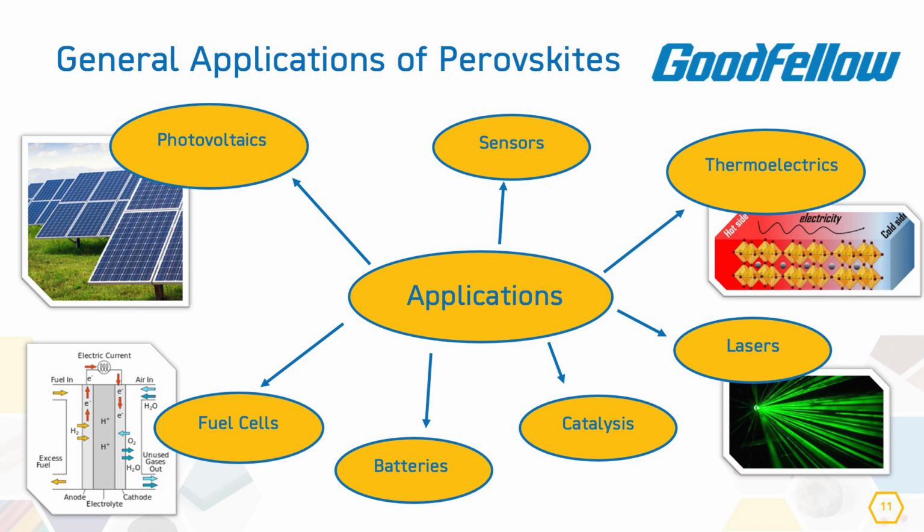Perovskites also have applications in lasers. Because of the compositional flexibility on the B site I've mentioned, atoms such as europium can be put on this site. And when a perovskite has europium in its structure, for example, and this perovskite crystal is then hit with energy, photoluminescence can take place, and the crystal can emit light at a specific wavelength. And because perovskites can be compositionally varied, you can vary the wavelength of laser light that is emitted, which is really important for some laser applications.